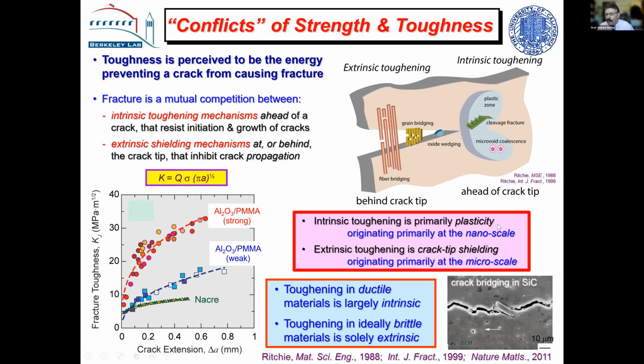And that's why there's a conflict between strength and toughness, because high strength materials have less plasticity, and therefore there's less plasticity to engage in this intrinsic toughening. These mechanisms, as I said, occur ahead of the crack tip, and they primarily originate at the nanoscale, the scale of a Burger's vector or something like that. If you look at a brittle material, though, those mechanisms don't work, because a brittle material in the limit is defined as one where you break a bond at the crack tip rather than emit a dislocation.